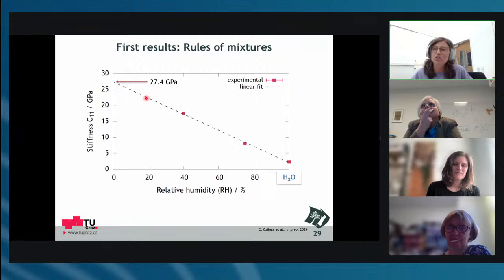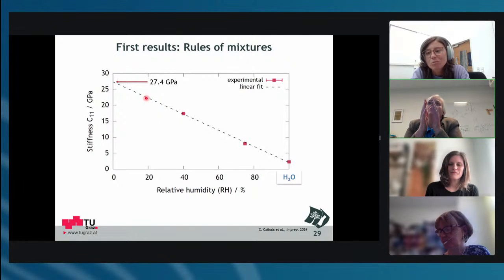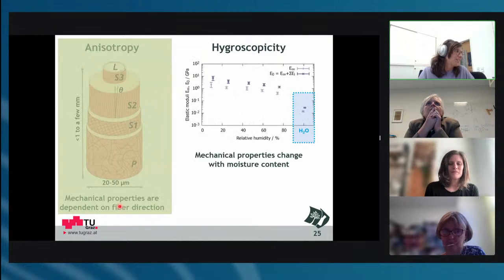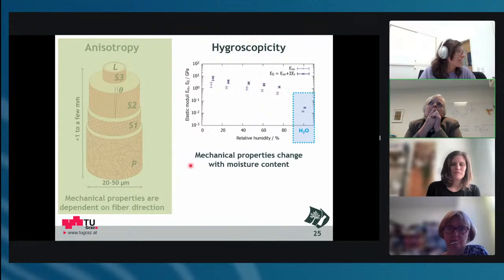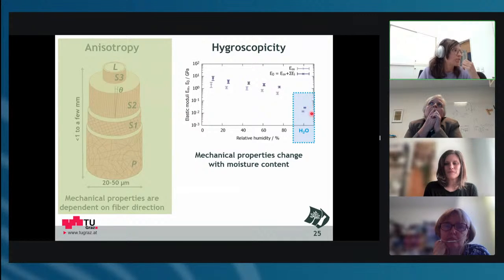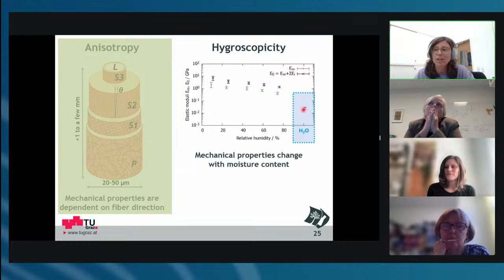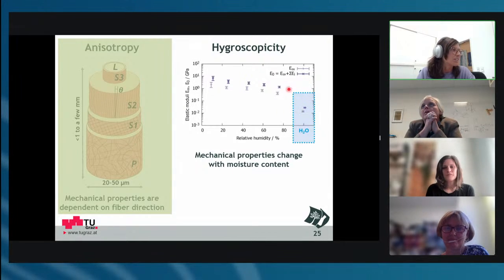And this is very often done. Do you use mixtures? I was thinking that the water maybe has a non-linear influence on the stiffness. So if you take up more water, I don't know how that will change. I know from the AFM measurements that I did, here in the transverse direction, so radial of the fiber, I did actually a lot of humidities and also measurements in water. When we change the relative humidity, we have a linear decrease of the elastic modulus, and then in water we have a drop. We go from around 1 gigapascal to 50 megapascal. So this is really a pronounced drop, and in water the fiber is completely different. But actually filling out these blanks here is really hard with any experimental technique, I would say.